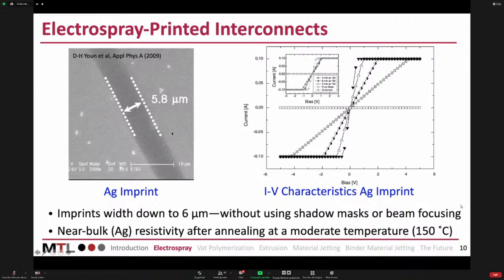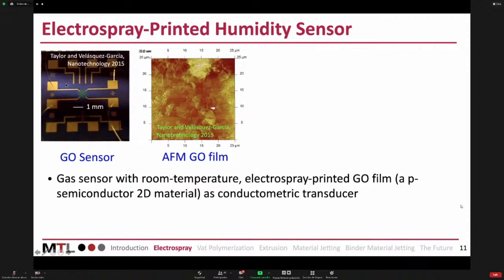So in our case, we have done things like this. This is a conductometric sensor. The sensing part is this dot, and this is a four-terminal device. If you are familiar with electronics, you know that this is a fairly common structure that you use to measure the electrical properties of a material. For example, you can put a voltage and measure a current, or the opposite, and based on that, you can see if there are changes in the resistance of the film because of some stimulus, for example, the chemical presence of a compound. And the printed part is zoomed here with an atomic force microscope.